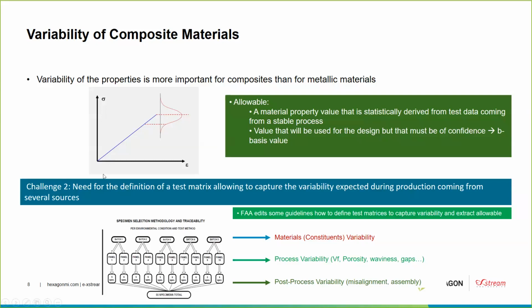That's the second challenge. If we want to be able to predict a distribution of results like the one we observe experimentally, then we need to have the possibility to define a test matrix that will allow us to capture the variability that is expected during the production and during the life of the coupon, and variability that can come from several sources. So we give the possibility in Digimat VA to define a test matrix. We follow recommendations coming from the FAA, and this test matrix will allow us to introduce variability at the material level, at the process level, let's say at the generation of the panel, and also what we call the post-process variability, the variability that can come simply from the way we test the coupon. That's the second challenge: the possibility to insert some variability during the generation of the coupon strengths.